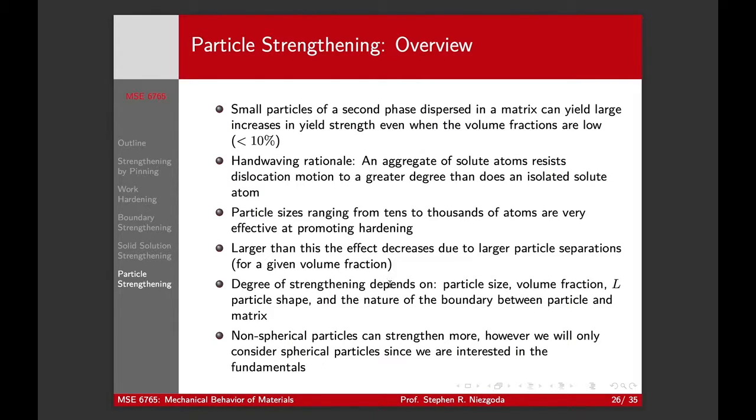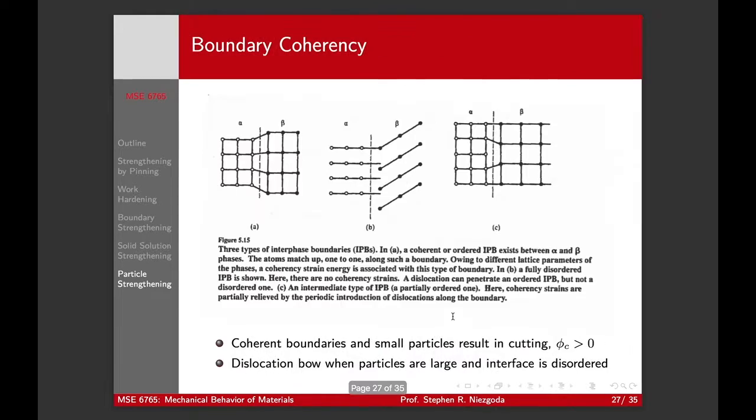And so the degree of strengthening depends on the particle size, the volume fraction, the number of particles that we have, the particle shape, the spacing between the particles, and the nature of the interface between the particle and the matrix. All right, we're going to simply talk about spherical particles only, because we're only interested in the fundamentals really. But non-spherical particles can have a larger effect, but they're much more difficult to describe quantitatively. And really, we only care about understanding the fundamentals.